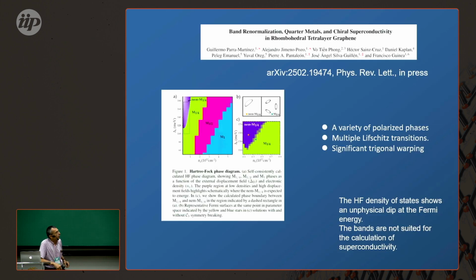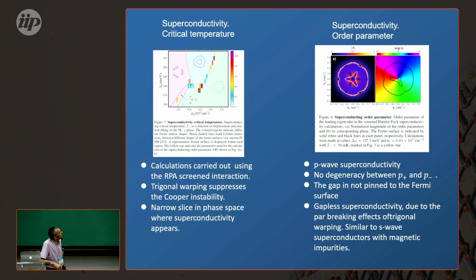We combine Hartree-Fock and superconductivity. The Hartree-Fock results are very consistent. You always find a half normal metal, a half metal, and a quarter metal as function of filling and displacement field. And inside the quarter metal, we got superconductivity, and it's a very non-trivial superconductivity because there is a strong trigonal warping.